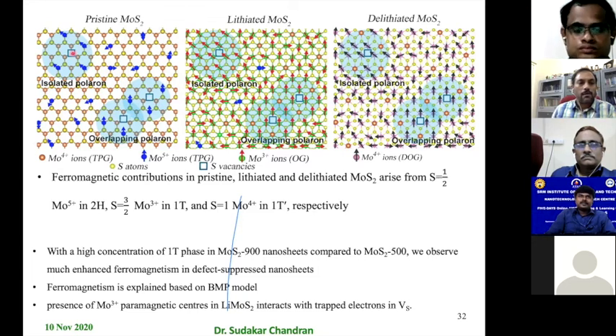Whereas when you have certain defects like sulfur vacancies, they always have trapped charges, and these trapped charges from the sulfur vacancies, along with the unpaired spins, interact and form magnetic polarons. Of course, these magnetic polarons can be segregated, but if you have a large concentration of these paramagnetic sites as well as the defects, then there could be overlap of these, like the one shown here. These two overlap. So when such overlap happens, within the magnetic polaron all the spins will be oriented because of the strong interaction. When they overlap, the interaction is now permeated, and then the spins are all oriented in the same direction. In the other regions, it is not.